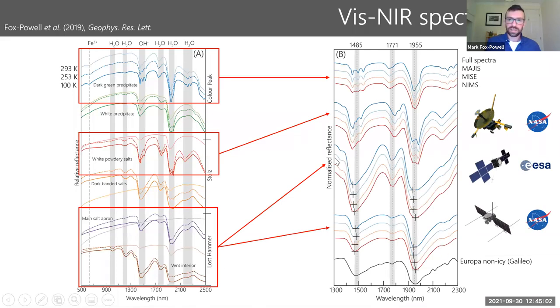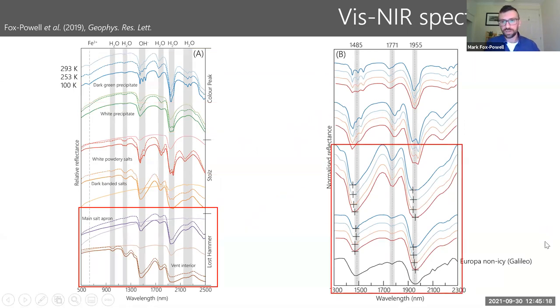What we did in this right-hand plot is we resampled the spectra, processed the data to match the spectral resolution of some upcoming and historical spacecraft instruments. And when you do that, you'll notice that these salts from Lost Hammer, which are these bottom two, reproduce the data from Europa, from Galileo, which is this black trace at the bottom. They reproduce the geometry of these main water absorption bands really nicely in terms of their width and their band minimum positions from the Galileo data. So this is a compelling spectral analog for this non-ice material on the surface of Europa.